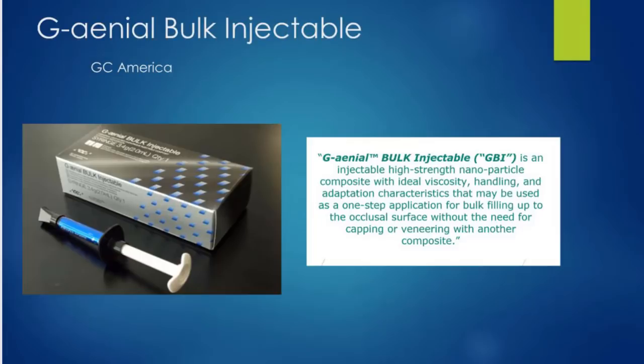There's some really interesting things about this material, and that is that it is a very high density resin that is now covered completely with this silane coating. And what that creates is this really homogeneous matrix of nanoparticles, which allows for great polishability while still allowing for really high strength and low shrinkage, as well as good adaptation to the proximal box.